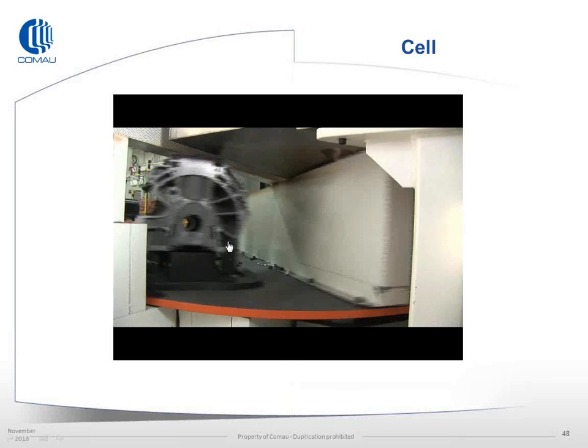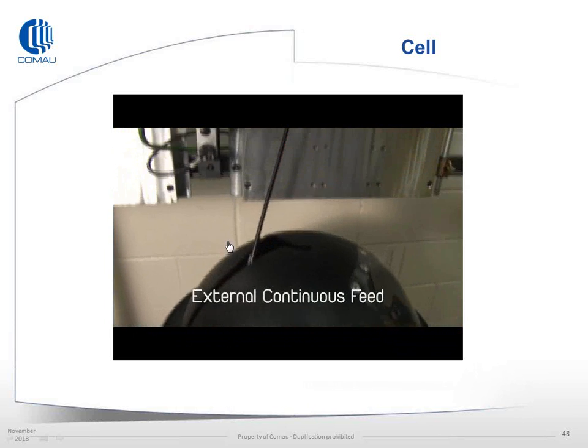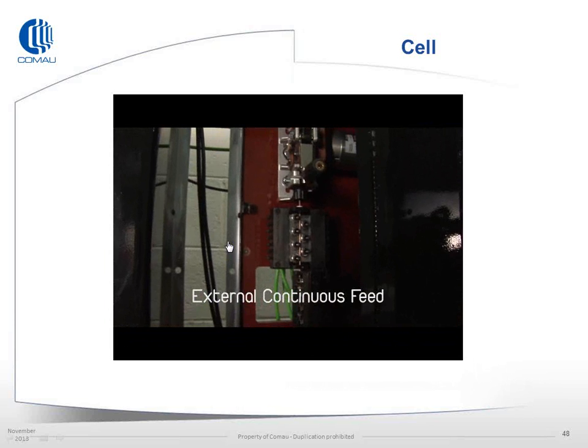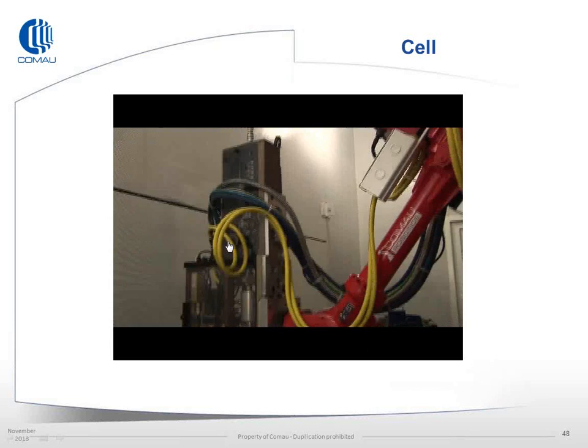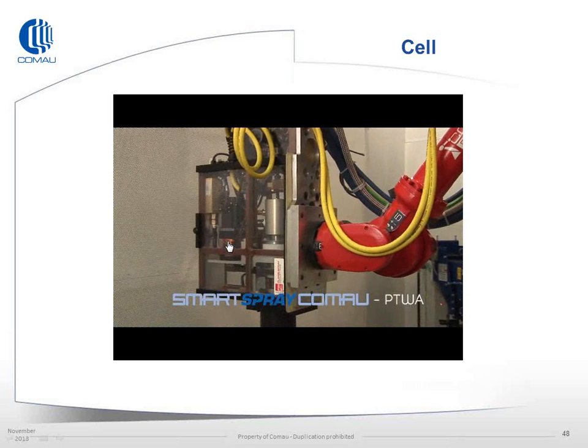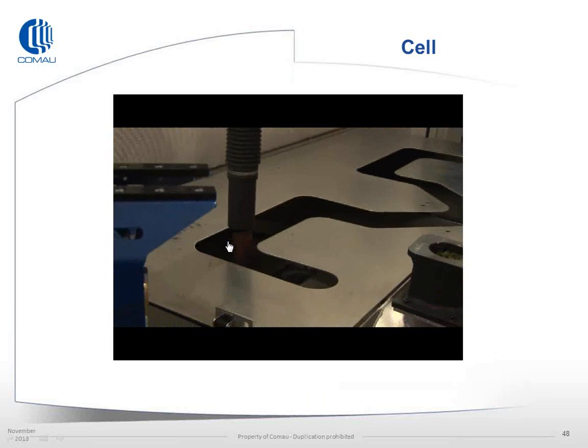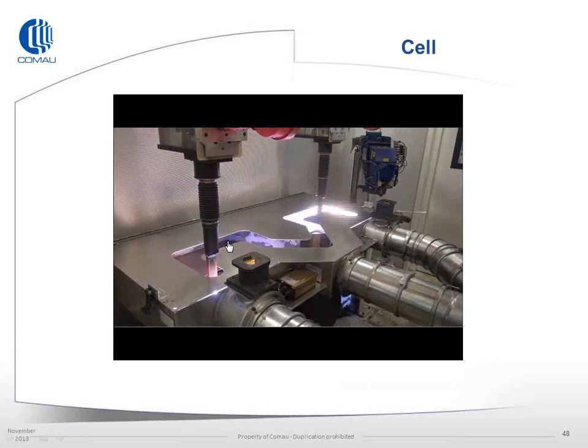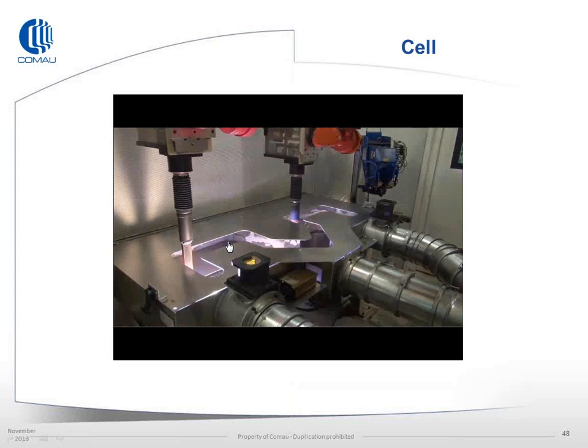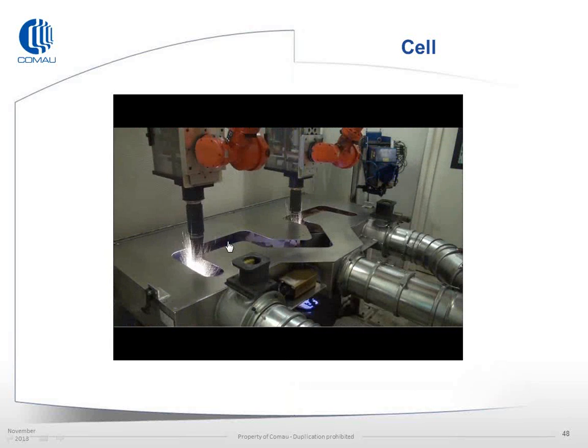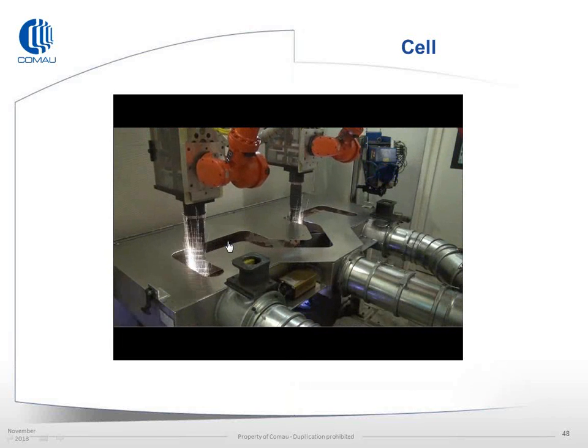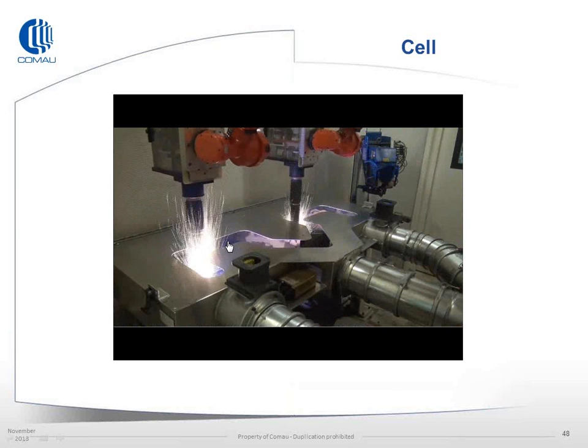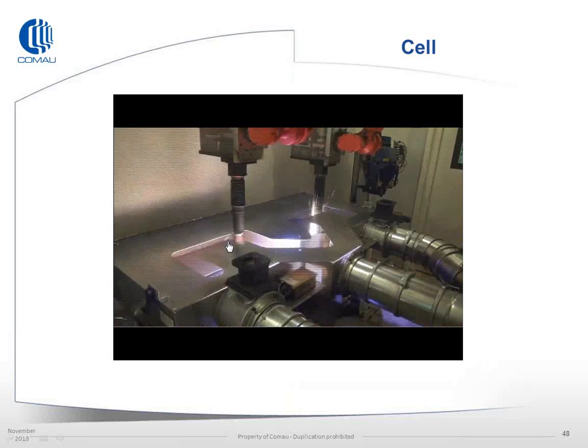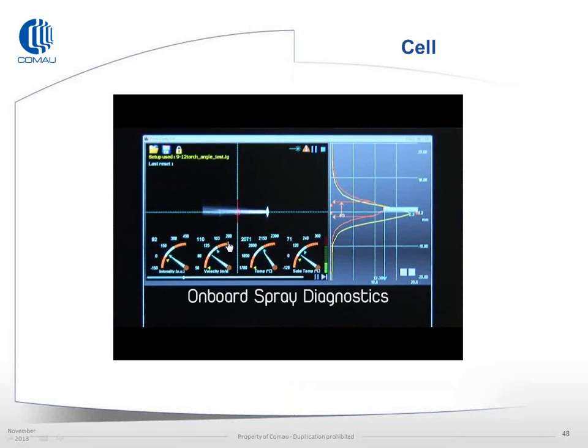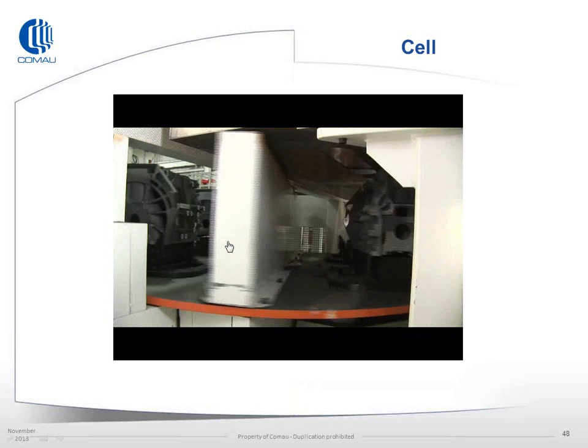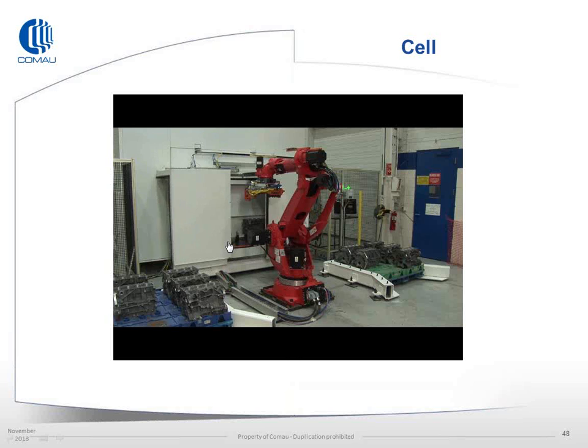The doors close, and in manufacturing we'd be using a continuous torch operation. The reason for that is the torch arc life is less affected, there's less usage of the cathode if we don't keep igniting it, and really the torch life is dictated by the cathode and the buildup within the torch. So what you've seen is we start both torches in a stationary position, spraying down into the suction system. Once we start spraying, we'll move to the coating locations, do approximately 4 to 5 passages depending on the bore size and bore length, and then repeat that for the following cylinders. In a manufacturing process, we'll keep the torches operating in between part change. For a prototype cell or initial prototype runs, we weren't running as often, so we were shutting down quite regularly.